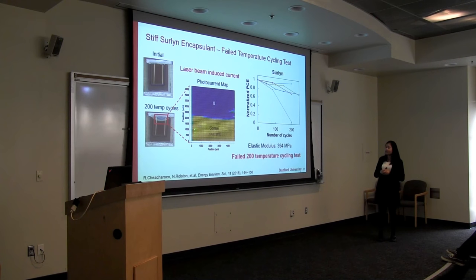When I looked at a solar cell, actually 5 different solar cells in 3 different packages of Surlyn, I saw that at least 4 out of 5 have more than 10% degradation. So we failed the 200 temperature cycling test with this Surlyn encapsulant. Why is that?